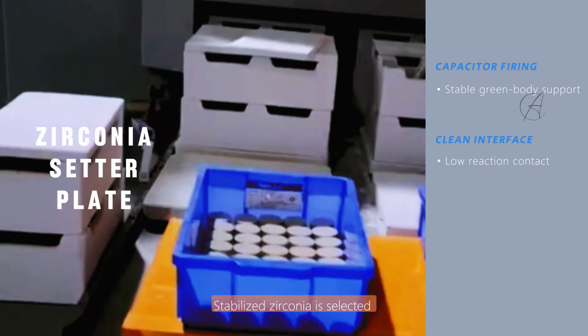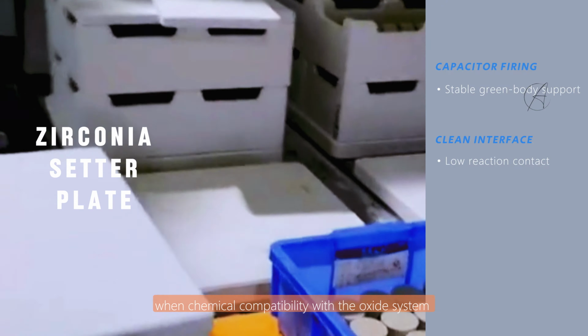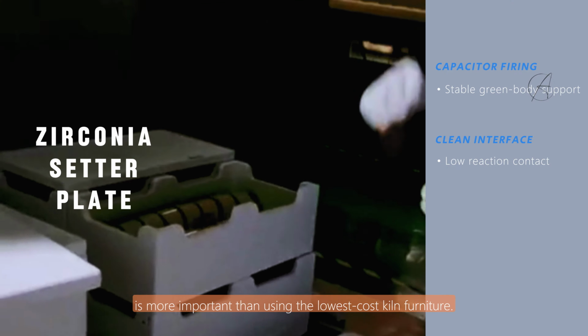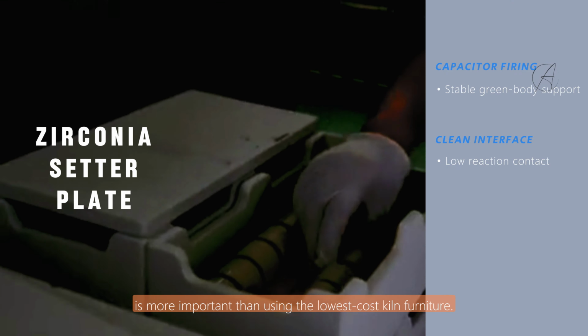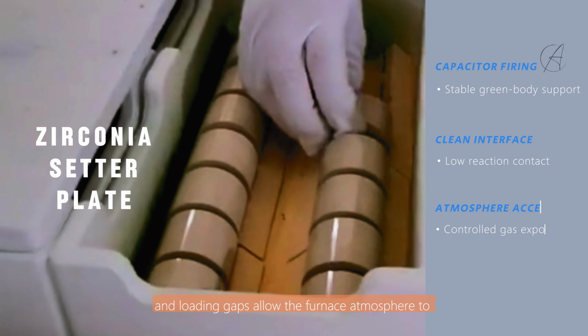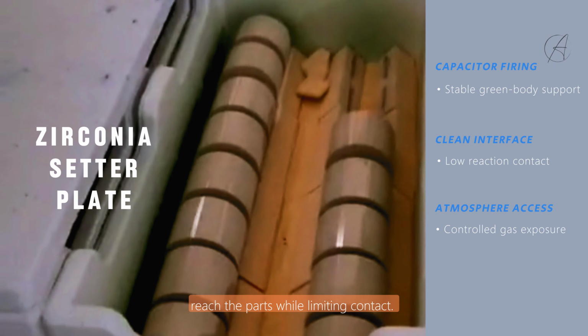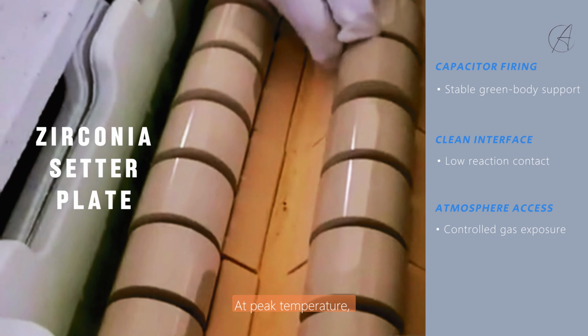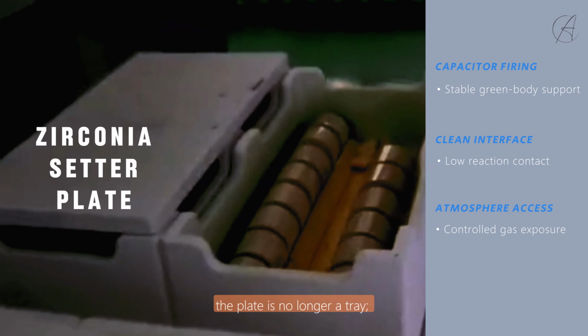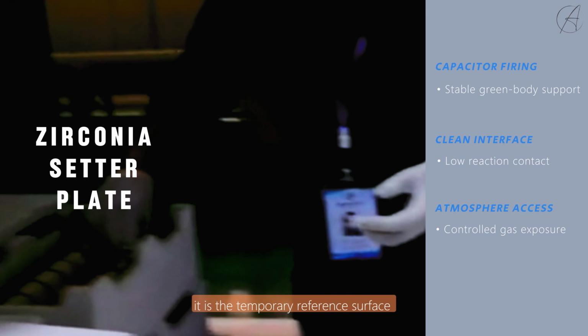Stabilized zirconia is selected when chemical compatibility with the oxide system is more important than using the lowest cost kiln furniture. Porosity, rails, and loading gaps allow the furnace atmosphere to reach the parts while limiting contact. At peak temperature, the plate is no longer a tray. It is the temporary reference surface that the entire sintering geometry depends on.